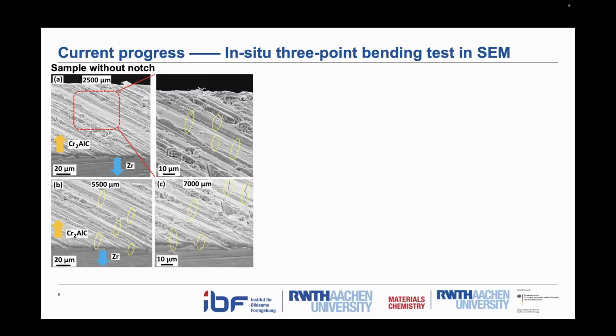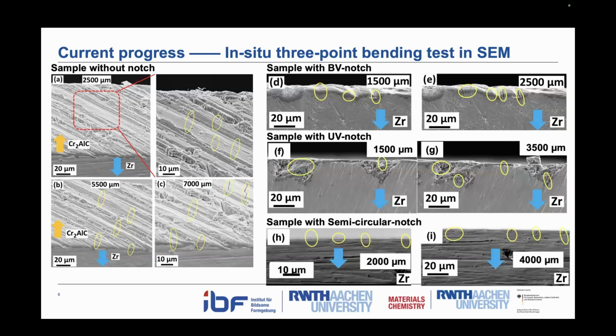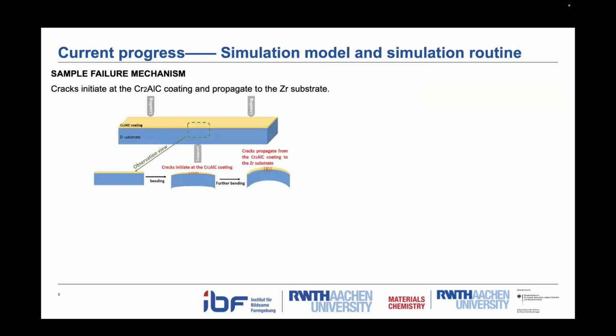We continue the loading, and when the displacement of the loading rod reaches 7,000 micrometer, cracks propagate from the coating to the substrate. This phenomenon was also observed in other samples with different geometries, for example the bi-notch, uni-notch, and semicircular notch. The differences only lie in the displacement when the cracks initiate in the coating and when the cracks propagate from the coating to the substrate. Based on our observations, we have identified the failure mechanism of this coating system: cracks initiate at the coating, and with further loading, they propagate from the coating to the substrate.